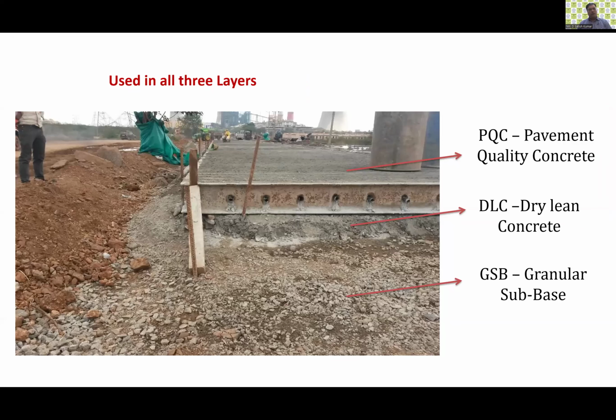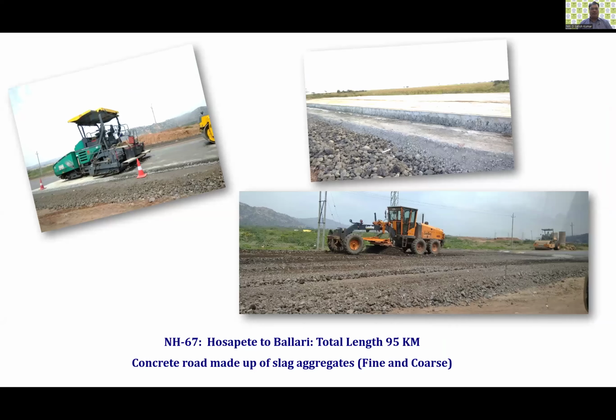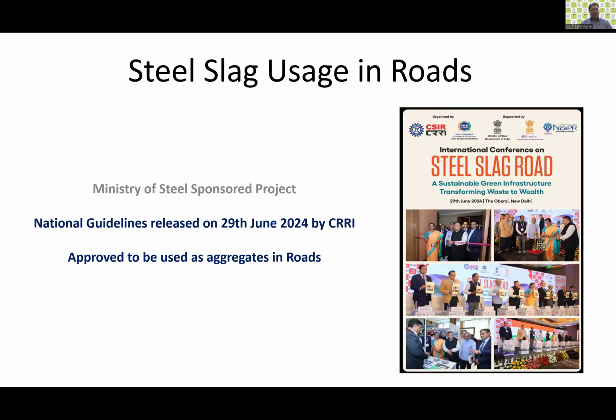We have also specifically started using them in roads, because roads is one of the specific areas where a large amount of these slags can be consumed, both in coarse and fine form, and all different layers it has been experimented. We also tried at NH67 Hospet Bellary, as I've shown you, and has been done using electric arc furnace slag and blast furnace slag, etc. But what most important thing which has been done in the recent year is all steelmakers were doing this slag utilization in their own domain.